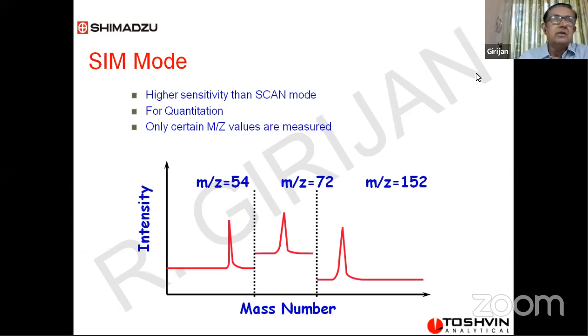A certain sample has given multiple fragments. And out of these multiple fragments, 3 prominent fragments were selected, 54, 72, 152. So when I am giving these 3 fragments, the software is actually making 3 different compartments. One for 54, second one for 72, third one for 152. And in each compartment, the DC to RF ratio is fixed. So we are keeping a ratio which can see only 54 in the first compartment.